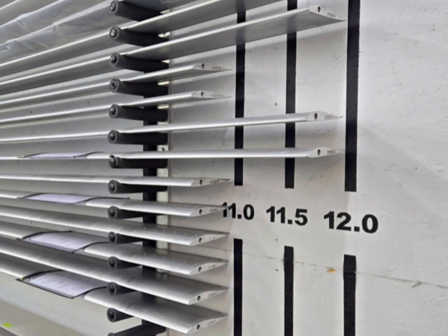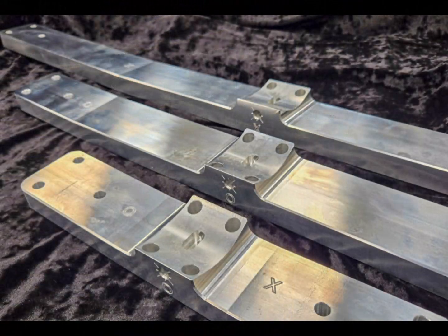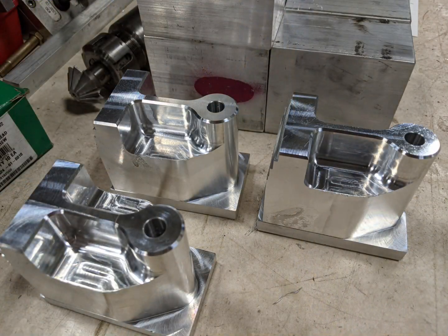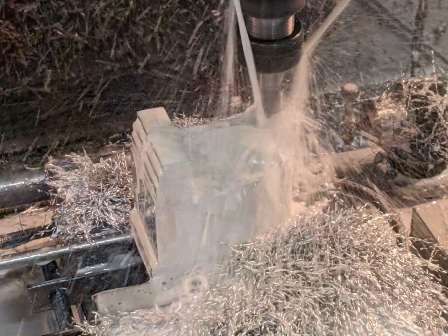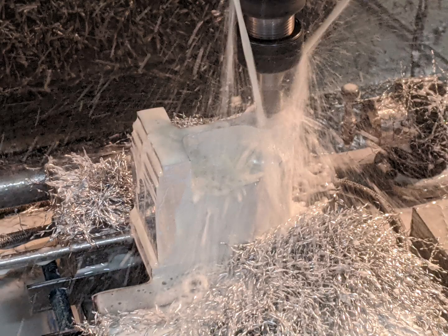We currently produce 11 and 12-foot blades. Combining these with a 1, 2, or 3-foot hub bar allows us to provide rotor systems ranging from 23 to 27 feet in diameter. The hub bar is machined out of solid 6061 T6 billet aluminum with a 2.75 degree coning angle machined right in. It's not bent. The hub blocks are also machined from solid 6061 aluminum stock.